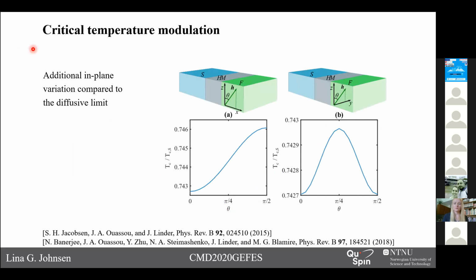Last, I want to show you some results we have on the critical temperature. As I mentioned earlier, it has already been shown that the critical temperature changes when we rotate the magnetization of the ferromagnet. The previous results are what you see in panel A, where it has been shown both experimentally and in the diffusive limit that we have a suppression of the superconducting critical temperature for in-plane magnetization compared to out-of-plane magnetization. What has not been shown before, and what we were able to show in the ballistic limit, is that in addition, we have a modulation in the critical temperature for in-plane rotations of the magnetization, where the critical temperature is further suppressed when the magnetization is along the cubic axis compared to when it is in the middle between the cubic axes.